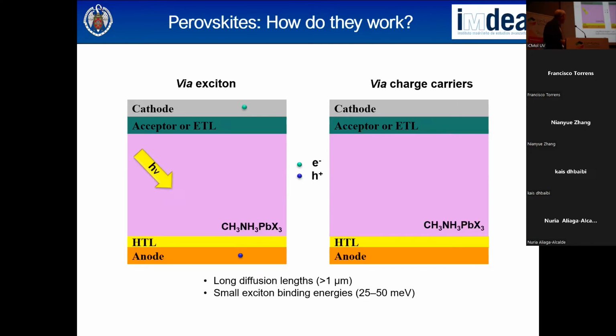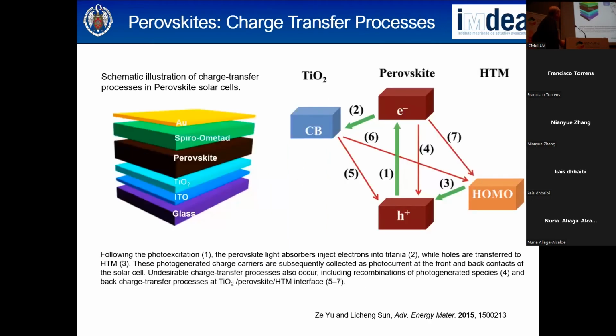What happens in the perovskites is that the active layer is a semiconductive material, and therefore, because of the small exciton binding energy, the separation of the exciton occurs immediately, and holes and electrons can move to the respective electrodes. Of course, they have to go through the electron transport layer and also the hole transporting layer, which are critical for these devices. This is the typical architecture: the active layer, the perovskite, sandwiched by the hole transporting layer, the electron transporting layer, and the 2 electrodes. One of them, of course, must be transparent in order to collect the sun energy.